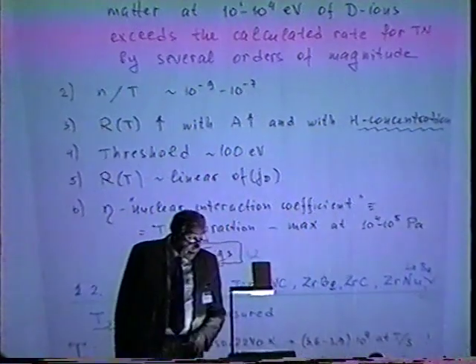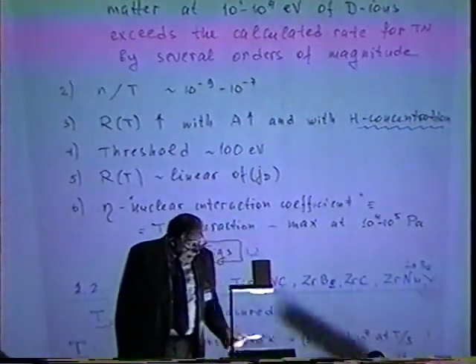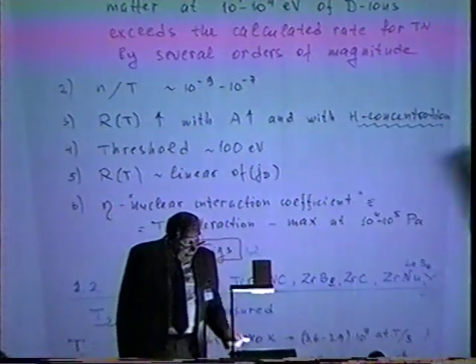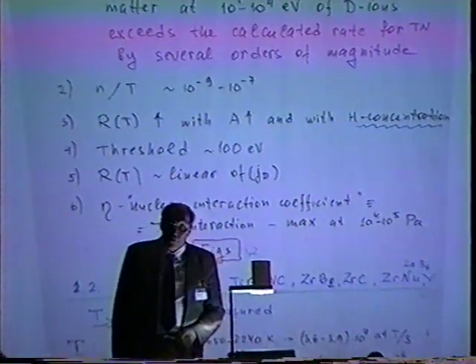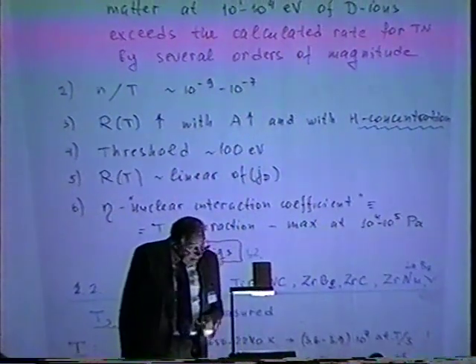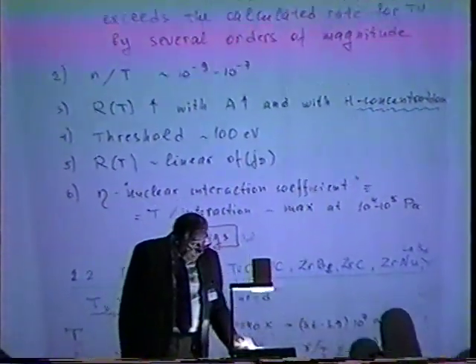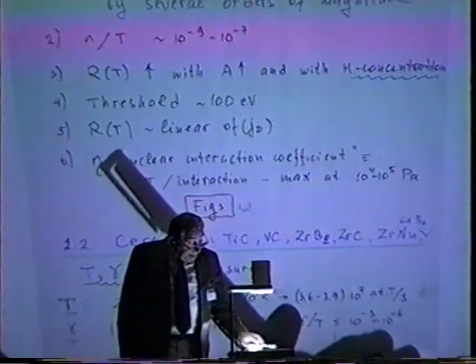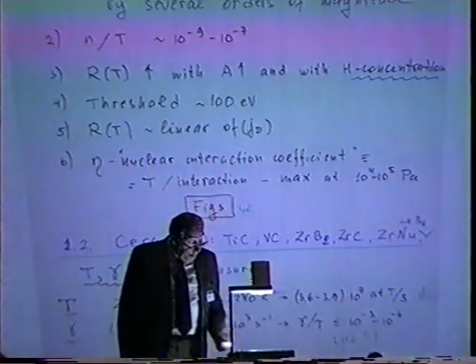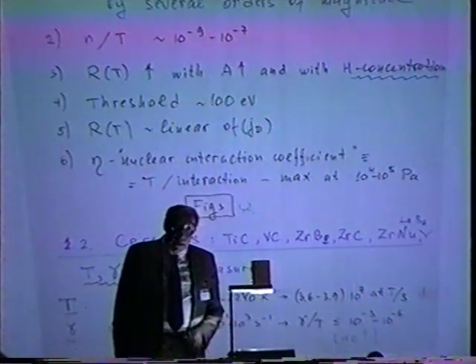Second, the neutron to tritium ratio is very small, typically 10 to the minus 9. The rate of tritium production increased with increasing atomic number of the target and with the concentration of admixture of hydrogen. They also observed some sort of threshold effect, and this threshold is about 100 electron volt. The next point is that the ratio of tritium production is more or less a linear function of current density.